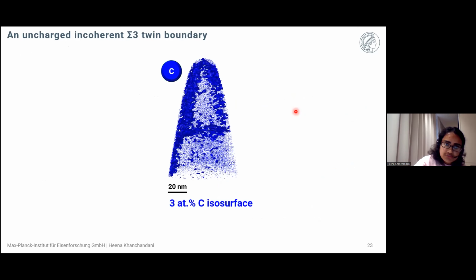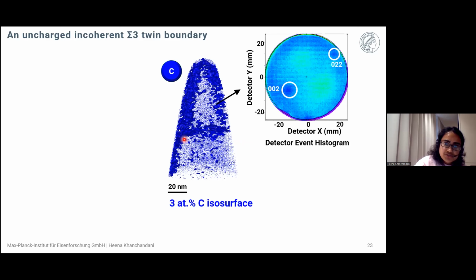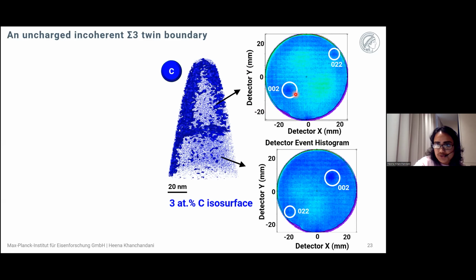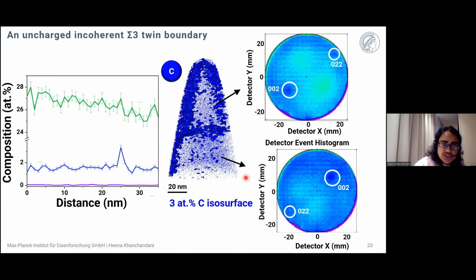An incoherent sigma-3 twin boundary was also analyzed from the uncharged sample, which has carbon segregation. So it was confirmed by the detector event map, where the inversion of 002 pole, and both of these poles show that it is a boundary in between, which had carbon segregation, but there was no oxygen at this boundary. So this also shows that the grain boundaries with elemental segregation, with carbon segregation, are more resistant towards the oxidation.